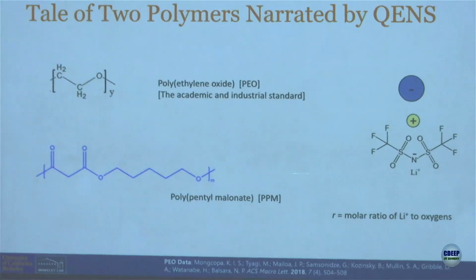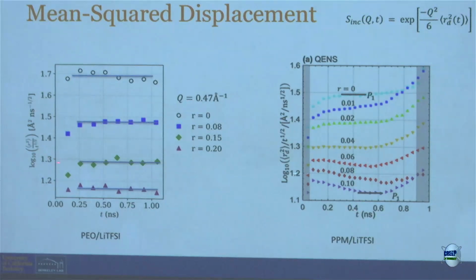And here are the data in the next slide for these two polymers, polyethylene oxide, or PEO, and polypentyl malonate, which is PPM. And again, this is the salt concentration. R squared divided by t to the half versus time. Okay? In PEO, you get beautiful plateaus. The plateau value tells you that adding salt from 0 to some value of 0.2, the mean square displacement has gone down for the same time. And this is because when you add salt, you get more friction because those ions are sort of sticking to the oxygen.